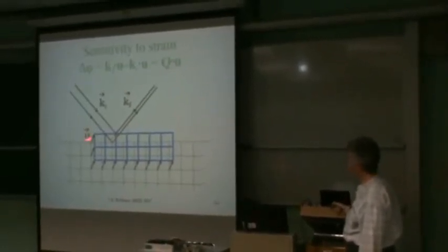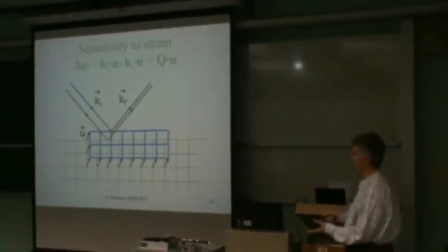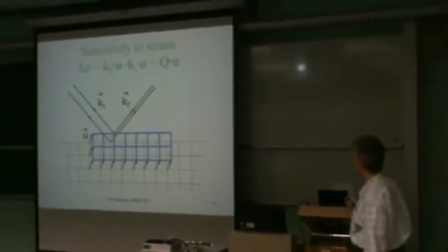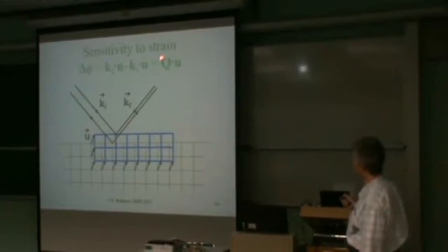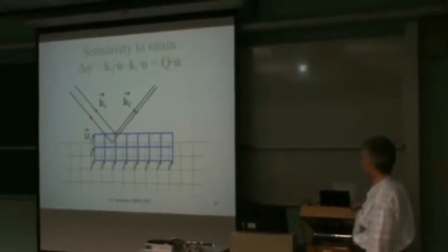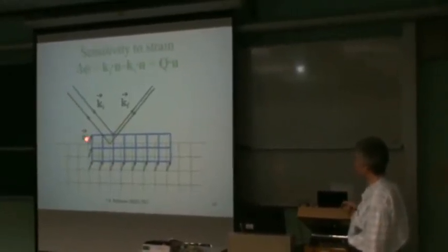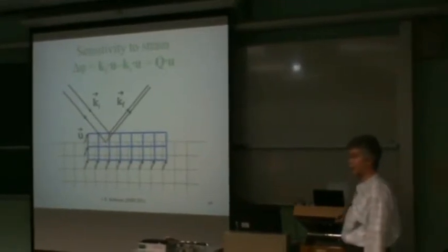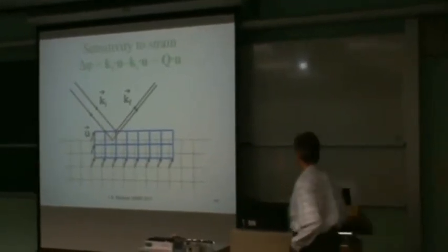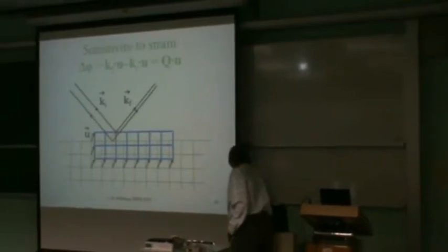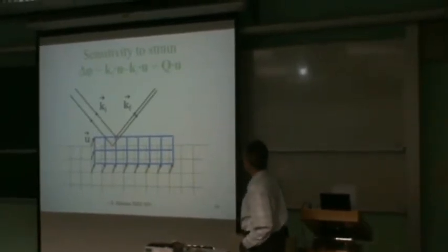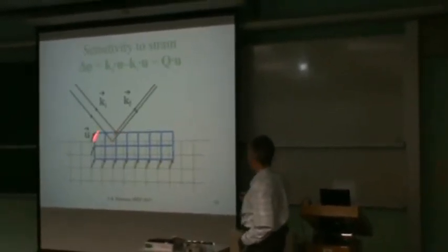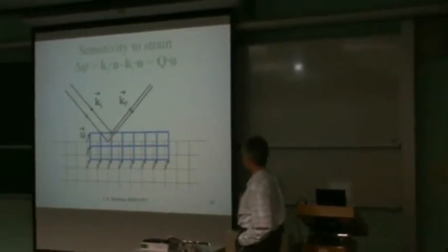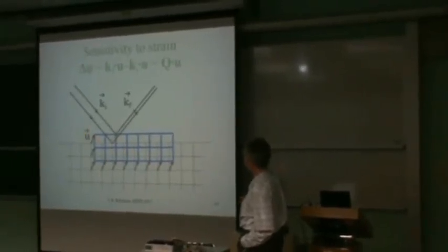So if you wanted to measure this displacement field everywhere inside the crystal, you would have to make at least 3 different non-coplanar Q measurements to get 3 different components of the U. That can be done, and I'll show you an example of that in a few minutes. Okay, so the phase of the image of this piece of crystal tells you about the projection of its displacement.